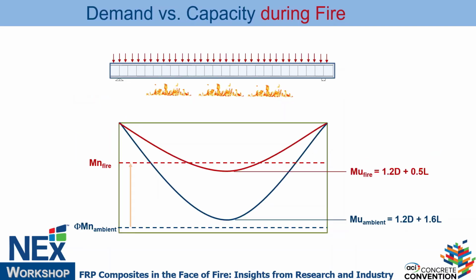So this chart that we looked at, what if I do this with FRP strength, and I found that it's inadequate? Well, that means I need fire protection, right? Now, why does this happen? Because there are two components to the equation, right? I have the capacity and I have the loading. If we're using FRP to repair, we're not increasing the load. Maybe sometimes it will pass.